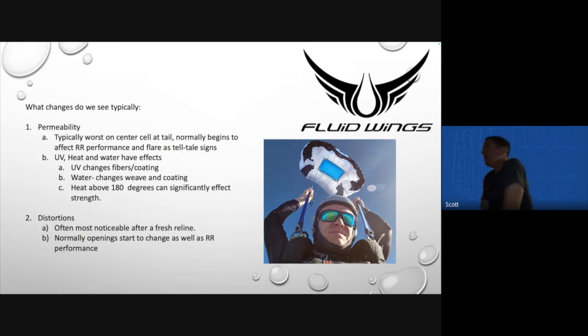So the way we've always been able to measure it is everyone talks about permeability. And it's something that we can measure, and it's definitely a wear thing. They seem to happen in tandem, right? So typically when we're seeing permeability, we start to see distortions. But there's no clean and easy way to measure the distortions, because it's in the fibers a lot of times themselves. And so you can't just measure the ripstops. It's such a small change for a small unit that you're not going to see dimensional changes.